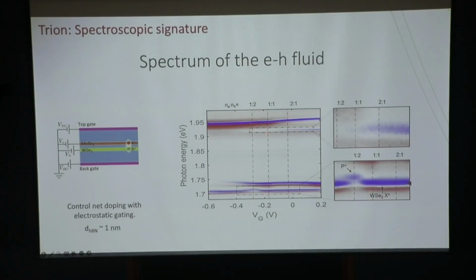We can see we have electron and hole doping. And then when we change the gate voltage to add excess holes or excess electrons, you can see something actually happens over here that corresponds to electron and hole densities of 1 to 2. What happens is basically the original trion peak disappears and a new peak appears. Something also happens at the electron 2 to 1 ratio, but it's weaker. So let's focus on the hole side, 2 holes, 1 electron.